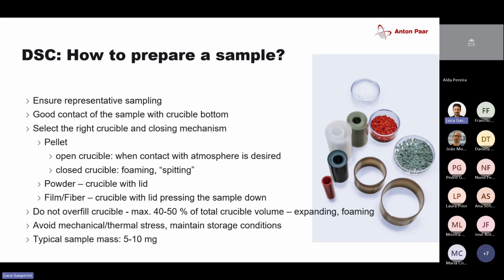Then you need to select the right crucible, because we have different types, different materials, different shapes, and closing mechanisms. We can either keep the crucible open or close it. It depends a lot on the application and the sample type. If we have a polymer pellet, then it's very easy. We can use an open crucible. If contact with the atmosphere is very desired, as in the oxidation experiments, then I'm not going to put a lid on the crucible, because I want the oxygen in the furnace to be able to diffuse into the sample and create the desired reaction.